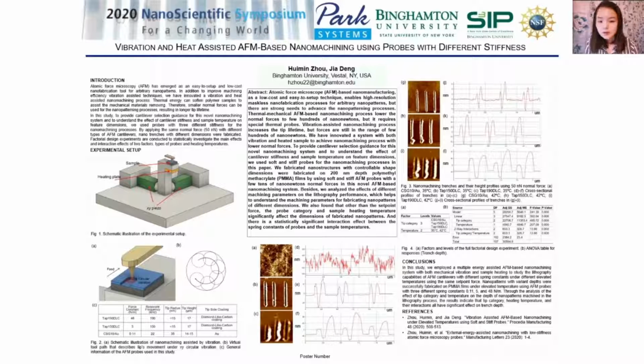We started with the softest tip, with the sample heated up to 35 degrees C. As you can see in Figure 3A, there are no trenches showing in the topography image, only some marks on the surface, with hardly any depth. Then we increased the temperature to 42 degrees C and did the same experiment. This time the trench depth is around 8 nanometers. The same experiment was repeated using TAP 150 DLC and TAP 190 DLC tips.